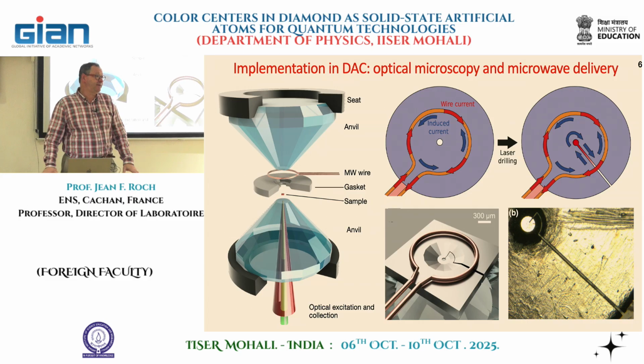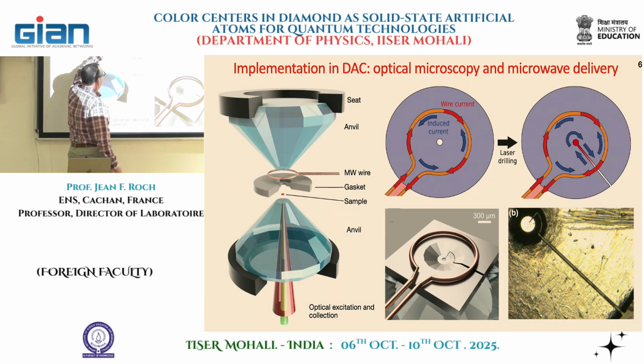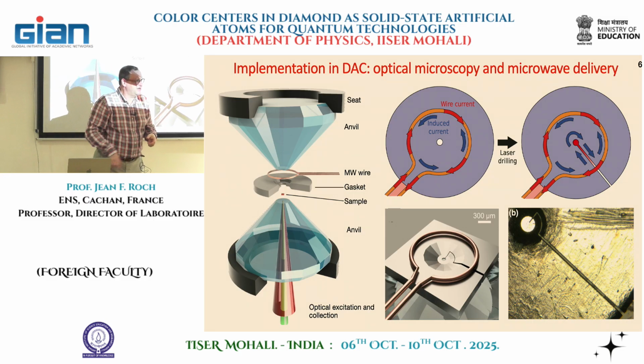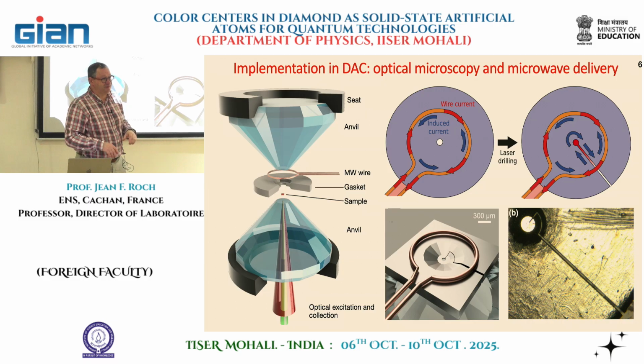So I showed you in the implementation of wide field magnetometry that we simply use a coil consisting of 2 turns of copper wire. So we simply do that: we put on top of the gasket this microwave wire that we made ourselves and hope that it works. When we tried, it didn't work at all. We saw no NV resonance. And then we thought a little bit, and then we found a reason for that.